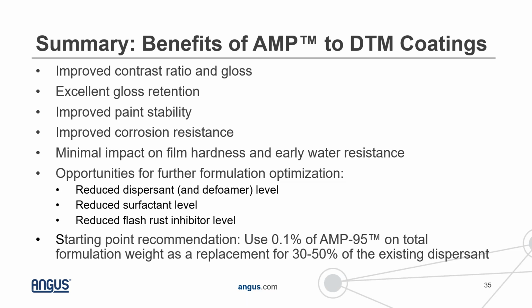There's also opportunities to adjust other formulation parameters as well. So as we mentioned, it's best to do this by using AMP in place of a regular polymeric dispersant. If you're reducing your dispersant level, there can also be opportunities to reduce your defoamer level. We also showed that you can reduce your surfactant level, in this case by about 25%, and still get some very nice improvements to corrosion resistance or salt soaking resistance. There's also potential opportunities to reduce the level of flash rust inhibitor, which can have very similar consequences towards coating improvements.